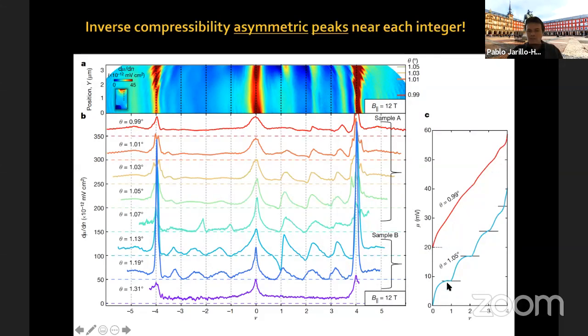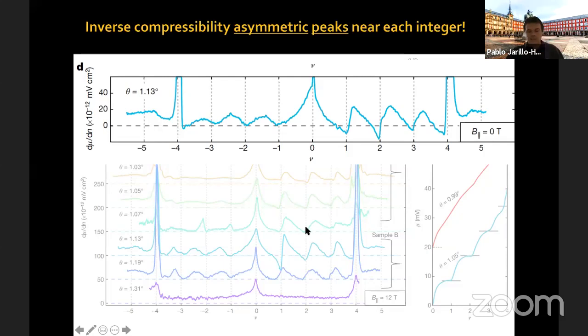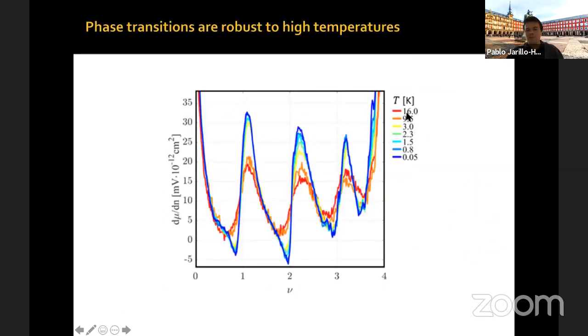If you integrate it, it means that in the chemical potential, you have these steps. These steps indicate a series, a cascade, we call it, of phase transitions, where your chemical potential is resetting at integer fillings. Now, the data that I showed before were at finite magnetic field, but in higher quality, more recent samples that we have, this occurs also at 0 magnetic field, and you have this very strong behavior. This behavior is very robust. I'm showing data here up to 16 Kelvin, but we have more recent data up to about 30 Kelvin. This is already happening at relatively high energies, well above typical correlated insulating states and superconducting states.